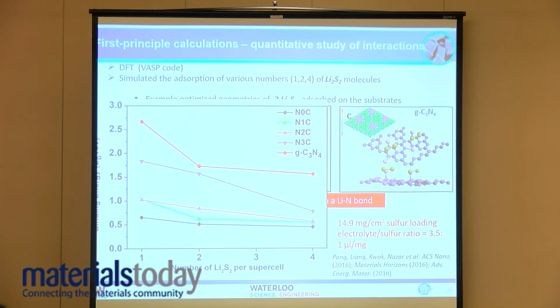And we're able to achieve almost 15 milligrams per square centimeter sulfur loading. And for those of you who aren't sulfur chemists, you probably don't know what that number means, but it's basically the highest ratio I think that we've achieved at a fairly low electrolyte ratio, again, in an attempt to make dense cells.